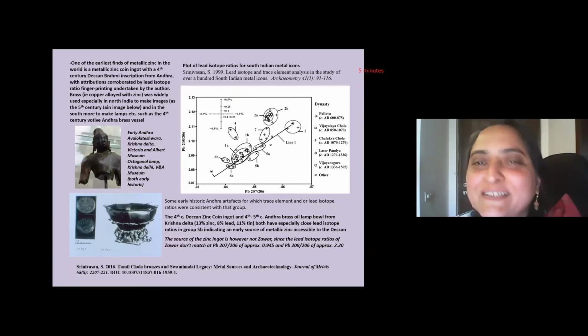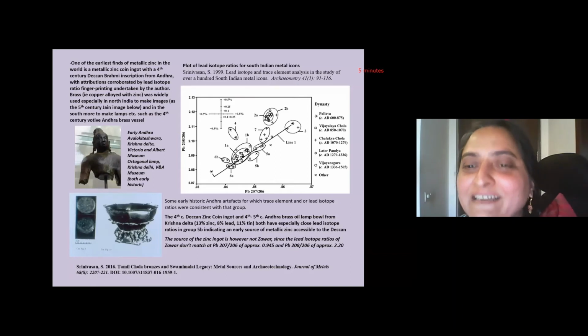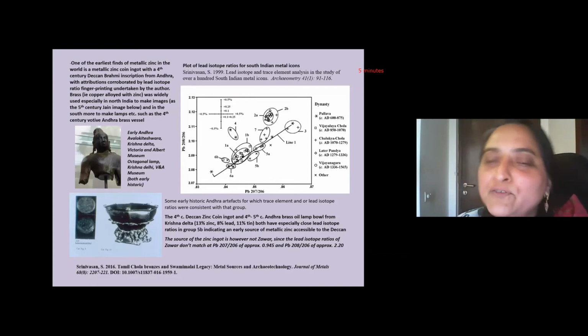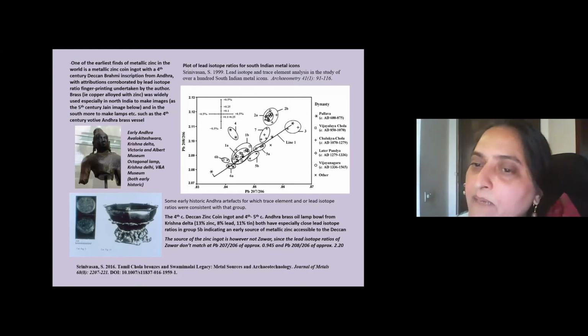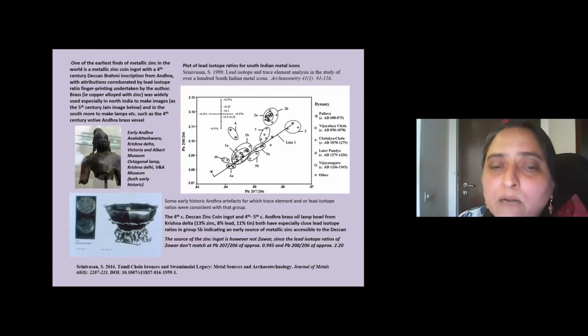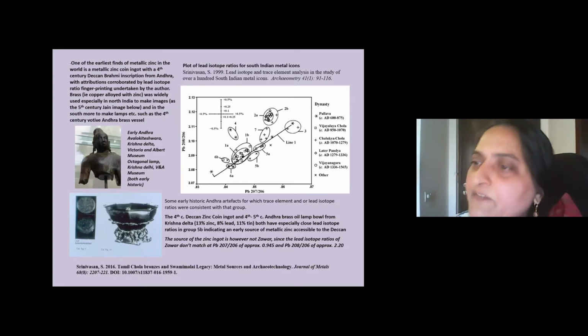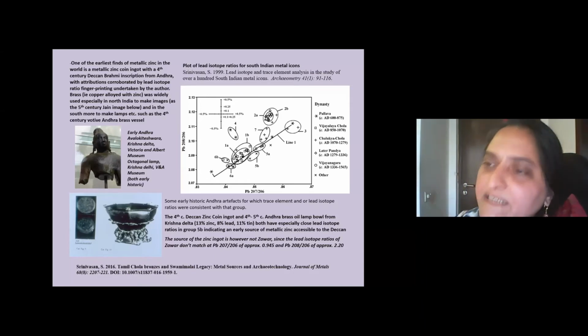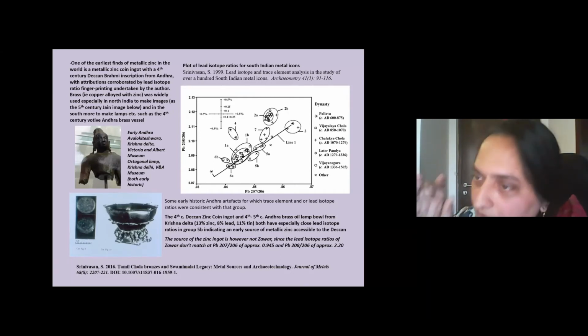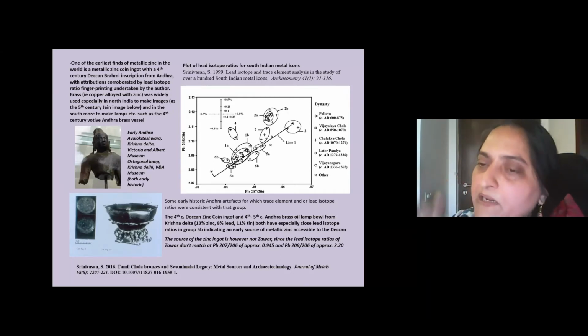Well, anyway, this lead isotope ratio technique is one where, if you have lead in an artifact, you can correlate the lead isotope ratios of the lead in the artifact to the ore source, because the isotopic ratios of different lead deposits vary in a very characteristic way. So what I was able to do by analyzing various groups of South Indian images was to create a lead isotope profile for different periods of bronzes, for instance, Pallava and Vijayanagara and Chola and so on. So I don't want to go into that too much.